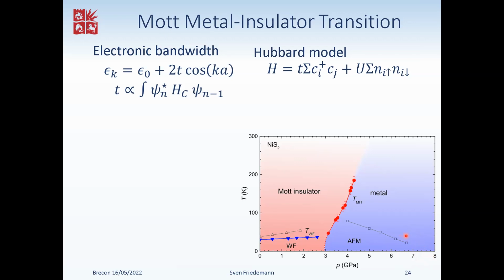Weak ferromagnetism, because it's a small moment. The antiferromagnetic phase boundary above, you haven't extended it to the right or the left. Are there other data points or other people's data points that extend that phase boundary? That's all we've got is on here. This is based on a small kink in the derivative of the resistance. There's no magnetic measurements that have been done under high pressure.